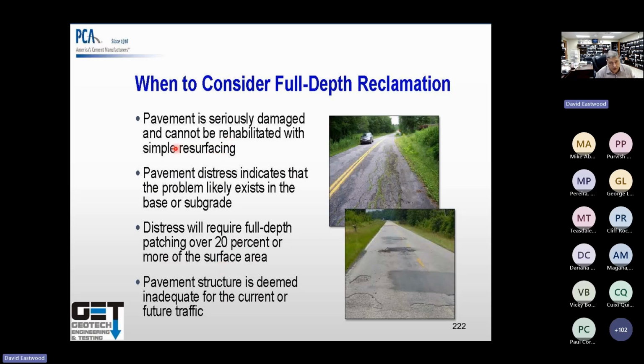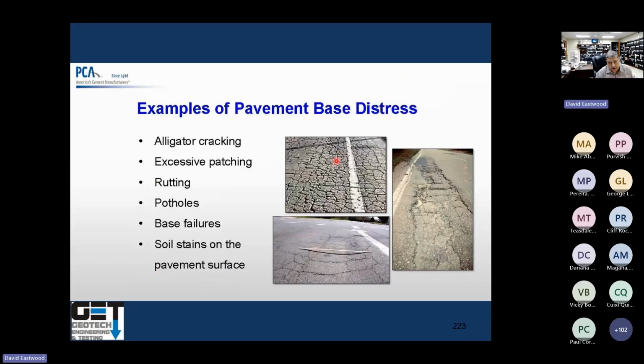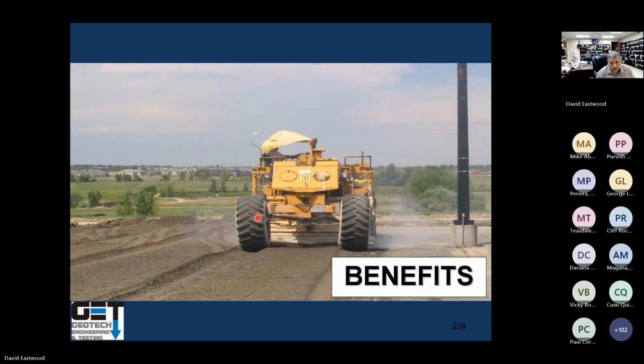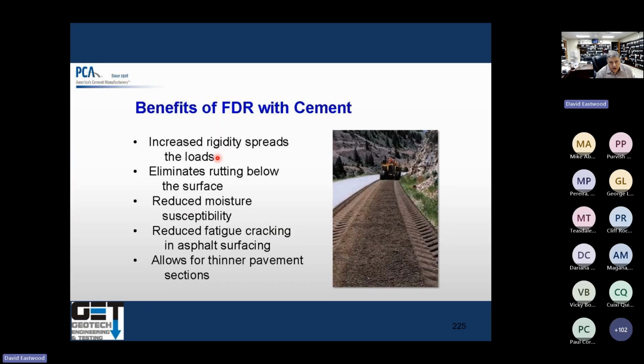Basically, you use full depth reclamation if the pavement is seriously damaged. Pavement distress indicates that the problem likely exists in the base or subgrade. Distress will require full depth patching over 20% of the area, or the pavement structure is deemed inadequate for current or future traffic. So that's our case here, that the pavement structure is not adequate for the future traffic. These are some of the pictures that show which types of pavements use full depth reclamation. Benefits, of course: increased rigidity that spreads the loads, eliminates rutting, reduces moisture susceptibility, reduces fatigue cracking, allows thinner pavement sections.